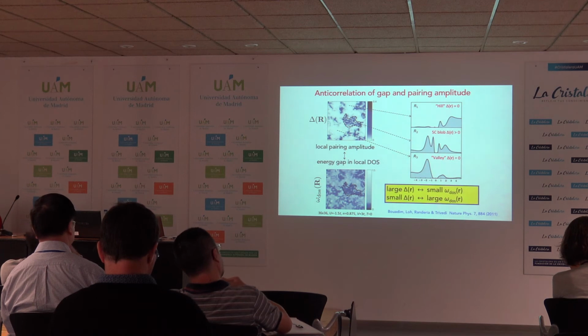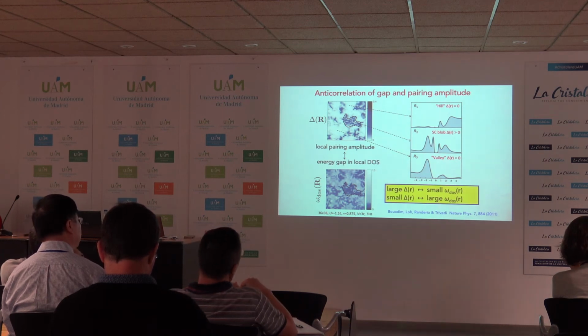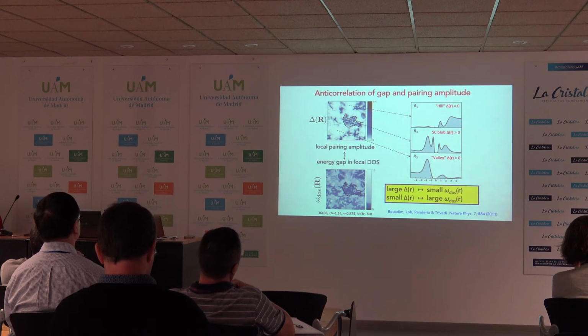And the reason for this is actually quite interesting. When you have a random potential, the states near the chemical potential are the ones that will be used to make these superconducting patches. So they obviously end up having the superconducting gap.